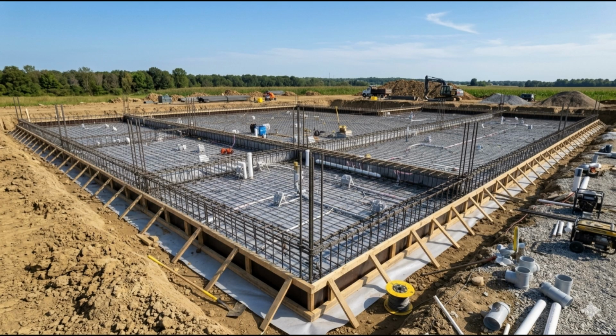He checked the cover at the corners of several spacer positions by pushing a cover meter probe against the bar and reading the display. The cover was consistently 35 mm to 38 mm, which was satisfactory. The top mat had been placed on stools, proprietary wire stools supporting the top reinforcement at the correct height to achieve 35 mm cover from the top surface.